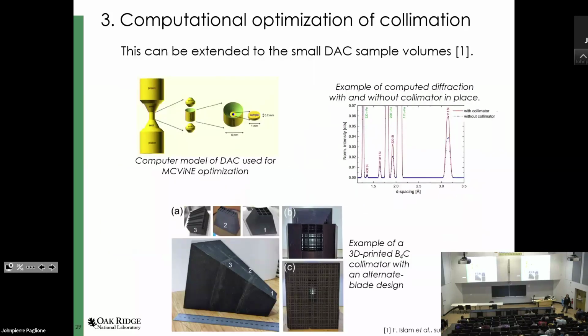We have also been extending that to the very small sample volumes that we use in the diamond anvil cell. So here you see a model that went into McVine, that simulation program. And then we 3D printed collimators from B4C. So they were getting very, very complex because 3D printing with B4C has a lot of limitations in what you can actually do. So our designs are getting more complex, blades are alternating, but overall the proof of principle does seem to suggest that this works. So this one was normalized, so now a higher sample scatter means that the collimation actually reduced the sample environment. So yes, these things work. They're still work in progress, but I think future instruments will incorporate more and more components like that.